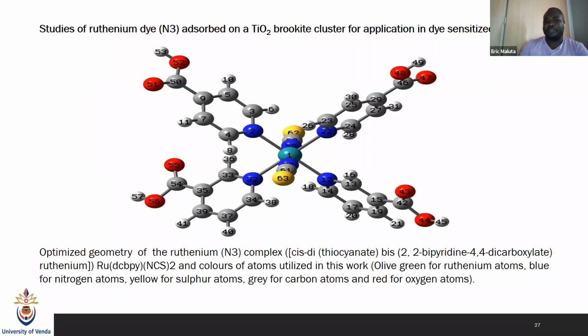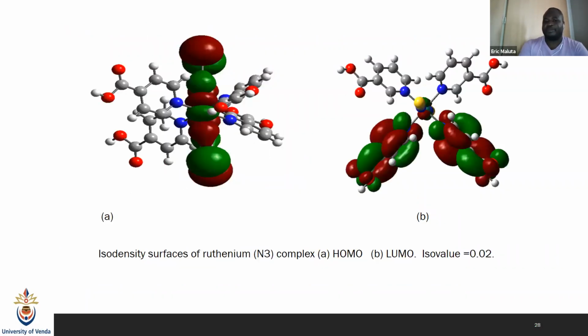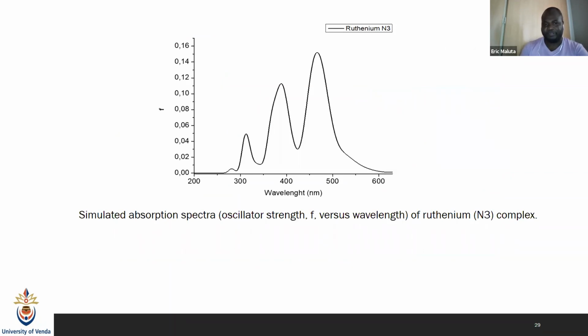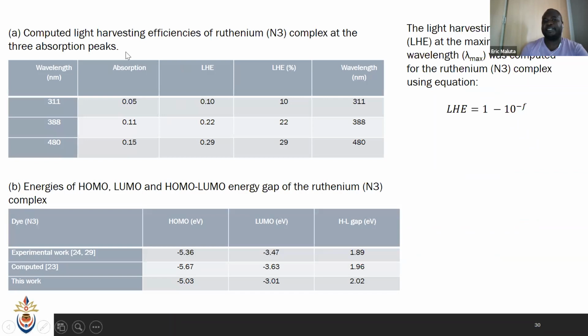Then going to the metal dye or inorganic dye, like ruthenium, which was one of the dyes used from the beginning of the invention of these dye solar cells, we also did the same: optimize it, and then calculate its properties. We look at its HOMO and LUMO to see where it sits before we adsorb it on the TiO2. And this is the structure showing the HOMO and the LUMO of the ruthenium dye. This is the simulated UV-vis, where we can see it also has different maximum peaks, where we have the lowest here, and it goes up like that. But then after getting that, we can also calculate its light harvesting efficiency.